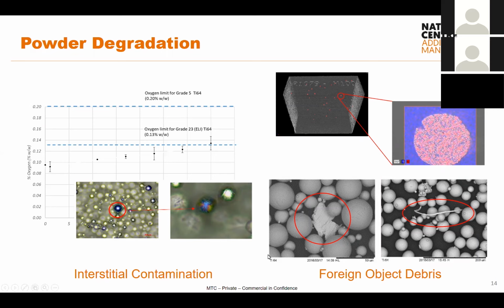The other issue, of course, is foreign object debris. Again, examples of real life parts built at the MTC. We can see this part here, lots of red dots on the image. Each of those red dots, this is an XCT image for those that aren't aware, each of those dots represents a high density inclusion. So a particle which is of higher density than the surrounding matrix material. They turn out to be tungsten. This particular part was built out of a material which from source had elevated levels of tungsten particles in it.